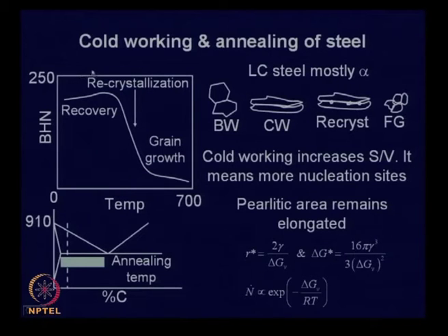And now, a quick look at how you control the grain size in steel. One method is cold working and annealing. We did talk about this: by cold work and annealing it is possible to get both a very coarse grain structure as well as a very fine grain structure. And how do you do it? This is a typical annealing curve. When you anneal a cold worked material, it has a very high hardness, and let us consider a low carbon steel, with very low carbon content, mostly ferritic.